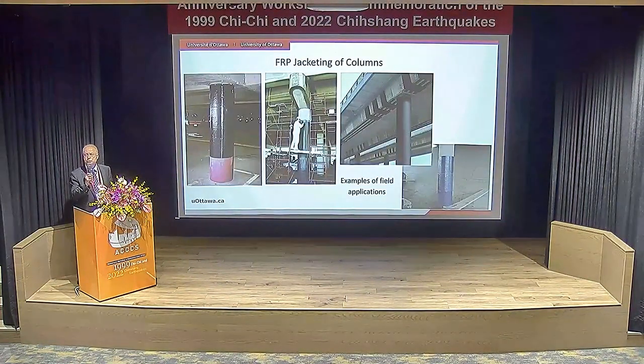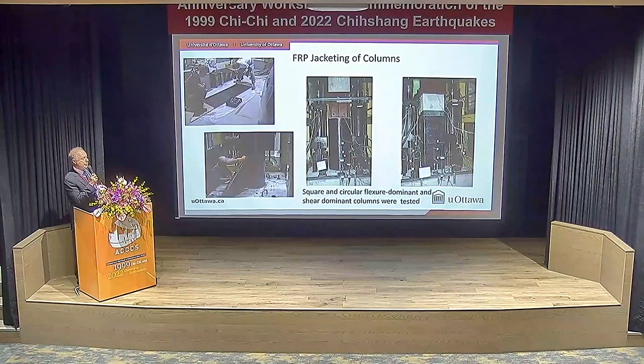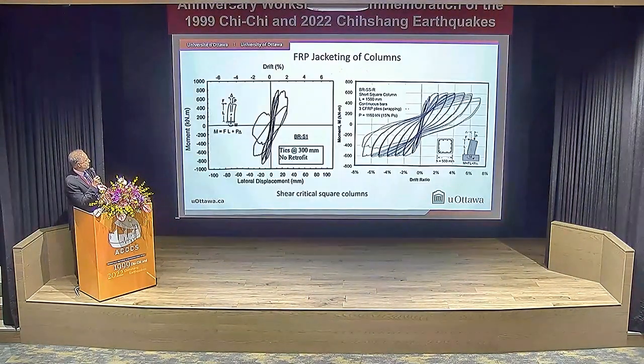Next, I'd like to go through FRP jacketing. This is a concept that has been well established in industry nowadays. You're all familiar with that. But we did extensive research in the lab testing shear dominant and flexure dominant circular and square columns, as well as rectangular columns. In fact, the outcome of this project has been incorporated in CSA S806, the Canadian standard for FRP jacketing. Once again, on the left-hand side, you see a shear damaged, shear critical square column. On the right-hand side, there was a significant improvement using FRPs.